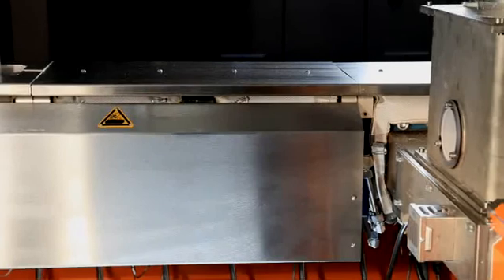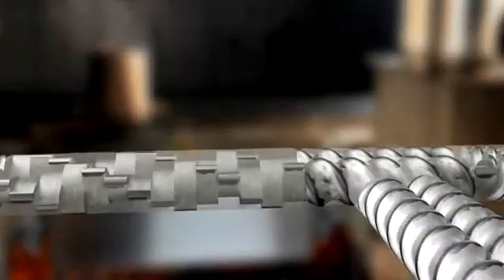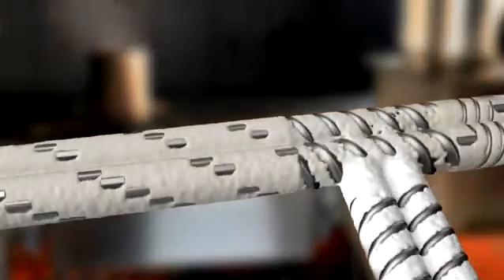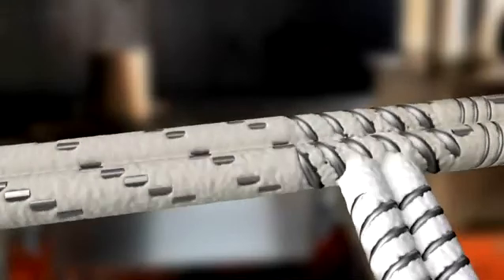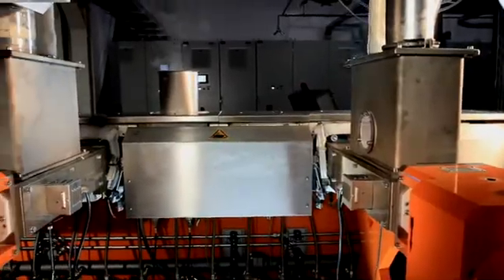the calcium carbonate is wetted, dispersed, and homogenously mixed with the melt. The air which was brought into the process can escape via the upcoming vent. Here, the screws are only partially filled and build a partial melt seal.